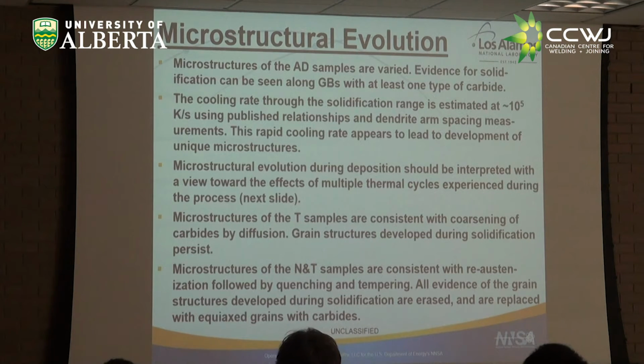There's also the notion, as I said before, about when I saw those interesting regions, did they occur during the production of that layer, or as the subsequent layers were put down? So it should be borne in mind that the microstructural evolution that occurs during this should be interpreted with a view towards multiple thermocycle effects. I'll show you a graph of that on the next slide. As I mentioned, the microstructures of tempered samples look just like the as-deposited, except with a lot more carbides. And the normalized and tempered looks exactly as it should. That would be an interesting microstructure to get.